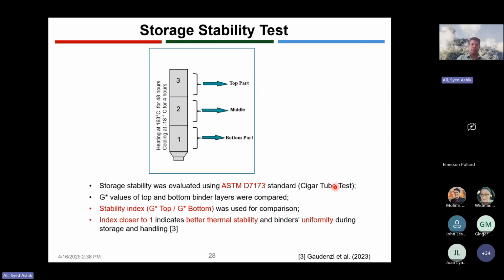So this is one important thing that we wanted to see: what is the impact of lignin on the storage stability, because we have seen several researches that reported that the storage stability could be an issue when we want to use lignin. So we did a test called the cigar tube test using the ASTM D7173 standard. In this test method, we used a cigar tube and filled it with asphalt binder, and then we put it into an oven at 163 degrees Celsius for 48 hours.